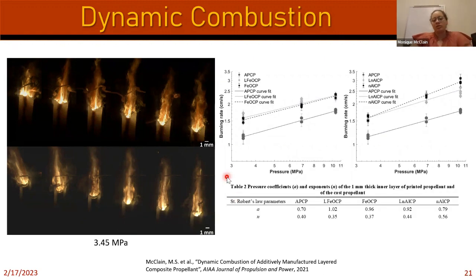So we did some burning rate experiments to explore that. Typically for burning rate experiments, we put that on a log-log scale, and we do a curve fit to figure out essentially the slope and then the intercept. Usually we care mostly about the slope. In propellant land, we want to see, is that slope reasonably stable or not? Usually we don't want it to be something like 1, but in general, the slope can give us information about whether these two materials are burning the same or similarly. So to orient everyone on this, I have both curves. On the left, we have data related to the iron oxide composite propellant, that's the middle layer of this.